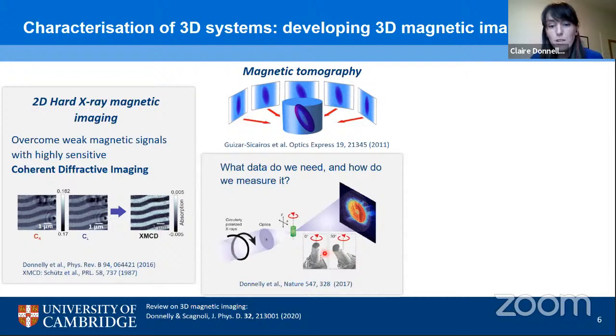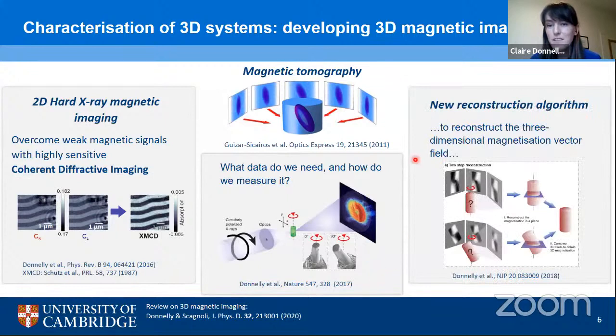In contrast, what we did here, at the cSAXS beamline at the Swiss Light Source, was measure an entire tomographic data set around one tomographic axis. We then tilt the sample by 30 degrees and we measure a second tomographic data set. And these two data sets combined give us access to all three components of the magnetization. Now, the third and last piece of the puzzle is combining all of this data to recover our magnetization vector field. And for this, we developed a new reconstruction algorithm in-house, which is based on the analytical formulation of the X-ray interaction with the magnetization, as a function of angle and orientation. And we based this on a gradient-based iterative reconstruction algorithm. And I'll go into a little bit more detail about this later in my talk.